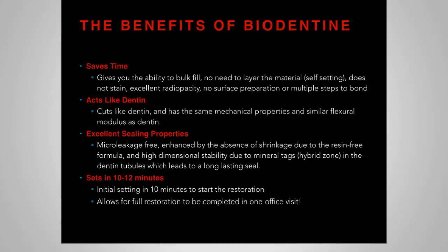And the key here, the big difference, is that instead of looking at hours for set time with MTA, you're looking at 10 to 12 minutes. So that allows you to complete this procedure in one office visit, and that's really important.